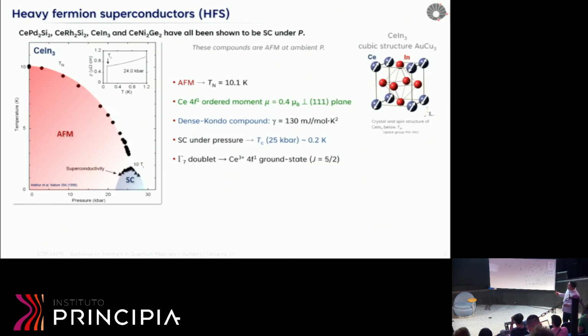So talking about CeIn3, specifically, this material orders at room pressure, or ambient pressure, at 10 K. It is antiferromagnetic with this magnetic structure here. It has a 4f ordered moment of about 0.4 μB in this plane. It's a dense Kondo compound with a gamma of 130 mJ/mol K². It is superconducting under pressure at about 25 kilobars. And also the ground state here is a Γ7 doublet ground state from the J = 5/2.